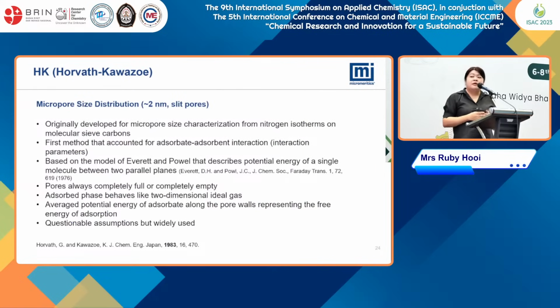The micropore distribution is about 2 nanometers in slit pores, so you are able to use the HK model. It was originally developed for micropore size characterization from nitrogen isotherms on molecular sieve carbons. It's very established and easy to use for model fittings. It's the first method that accurately accounted for the adsorbate interactions within the parameters, based on the model of Everett and Powell describing the potential energy of single molecules between two parallel planes. However, with this, the pores are always completely filled or completely empty when we desorb them.